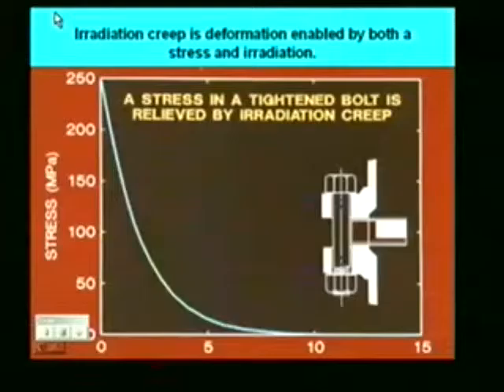So for radiation creep, we need two things. We need a stress and we need a radiation field. To put it in perspective, if we tighten a bolt, in this case we're preloading it to a stress of 250 MPa, it's a pretty tight bolt, and irradiate it, by the time we get to 10 dpa, 10 displacements per atom, we've completely relieved the stress in that bolt. So one thing it's telling us, if you're going to fasten materials in a high flux region, don't bolt it.